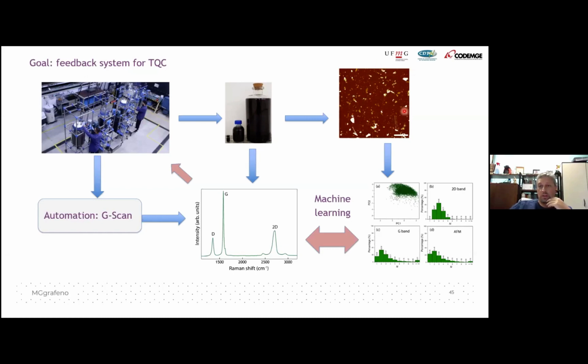If we go to the tabletop measurements, like for the lab, if we take our graphene, we deposit our graphene in a silicon substrate, we measure the AFM, the Raman, we get all this data. We are working with machine learning to understand how this connects to the spectrum that I showed at the beginning, that we just measure from your suspension, okay? If you measure your suspension, you get this. How does this connect to all this information? There's a lot of machine learning that can tell us this.